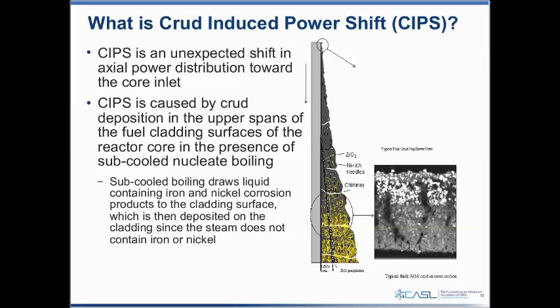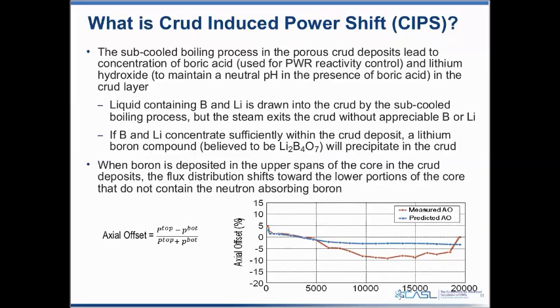That subcool boiling process then draws iron and nickel in toward the cladding surface and results in crud deposition there. As that crud gets thicker, and as we continue to have subcool boiling in the porous crud layer, we also now have a mechanism to concentrate other impurities within that porous crud layer.